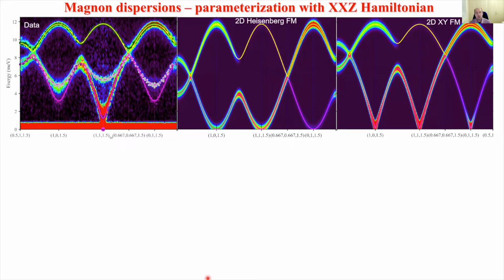So if we start to parameterize this data, we consider first a single honeycomb layer with Heisenberg interactions, as I described in the introduction. So there's a magnetic Bragg peak here. There's the acoustic branch, which is quadratic for Heisenberg interaction, and this is one of the touching points. So this has some resemblance to the data in that there's a strong mode coming down here, and this is the touching point here. However, the data clearly shows near linear dispersions. So this could be explained by considering a strong easy plane part of the interaction. So if we consider an XY ferromagnet where spins interact only in the XY plane, then we get the linear dispersion.